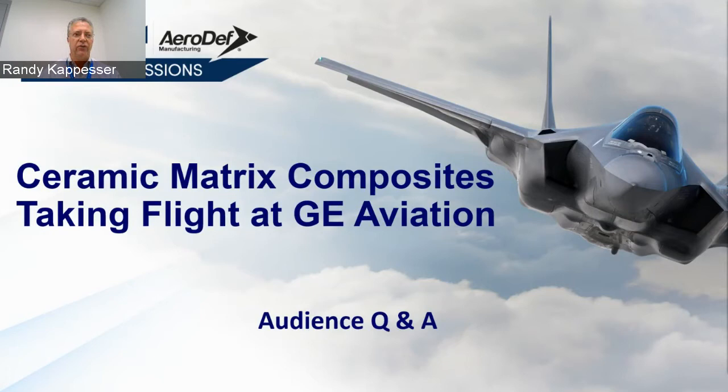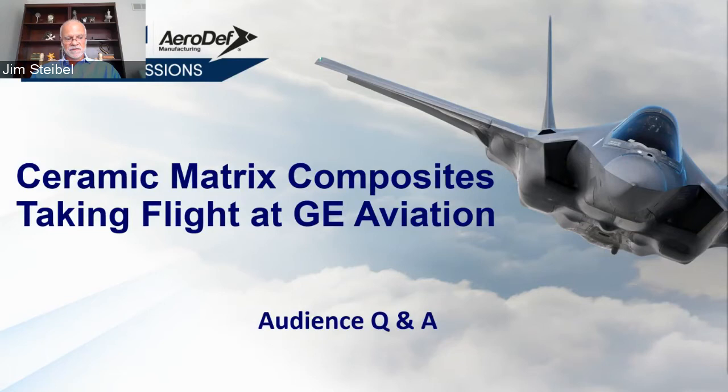Sure. The good news is that the machining processes that are traditionally used on metals are all applicable, even things like electro discharge machining or laser drilling or many of your more traditional turning and grinding operations. Really, in all cases, though, it takes a fair amount of development to apply those to a much harder material, a material that has a machining tool market in and of itself because it is a machining tool. So we are enabled by alternate machining tools like diamond coated in the case of your grinding or turning, or in the case of EDM, maybe changing your electrodes out and so on. But really, in all cases, we're able to utilize these different types of methods that are commonly available.